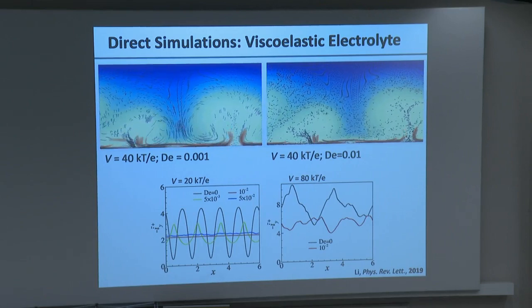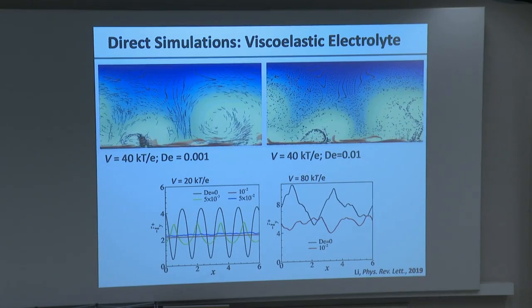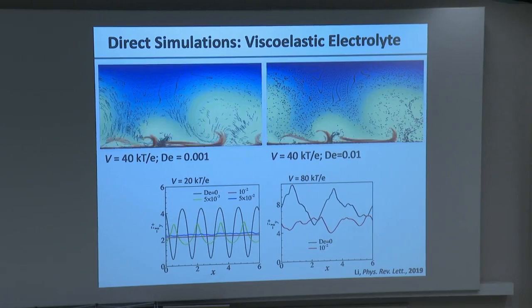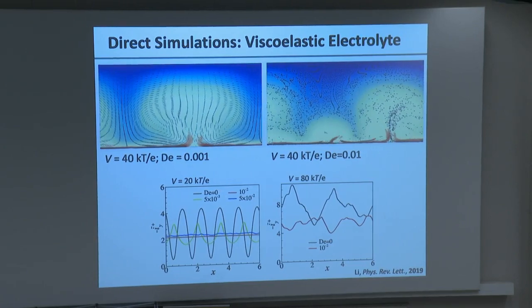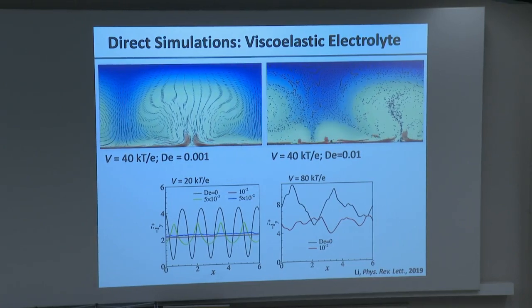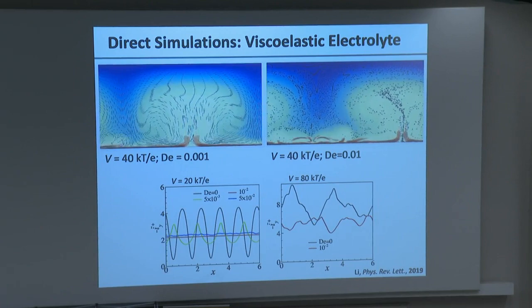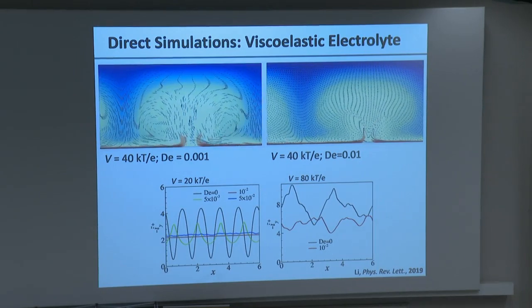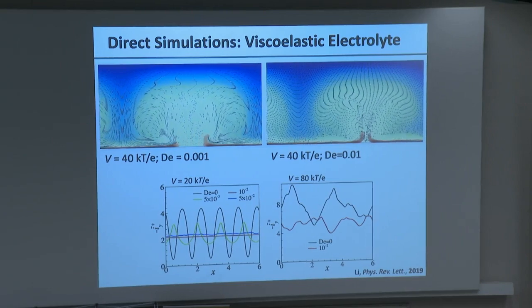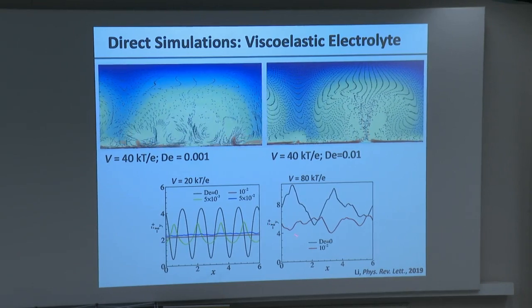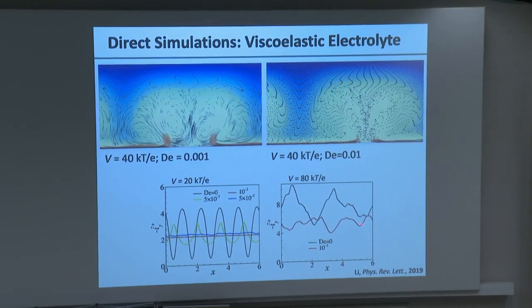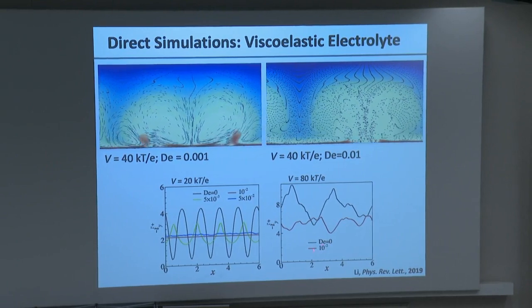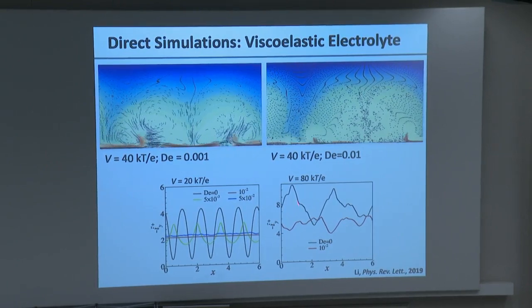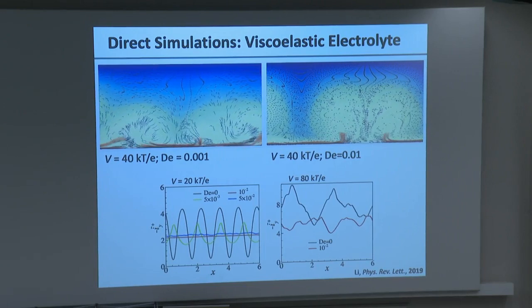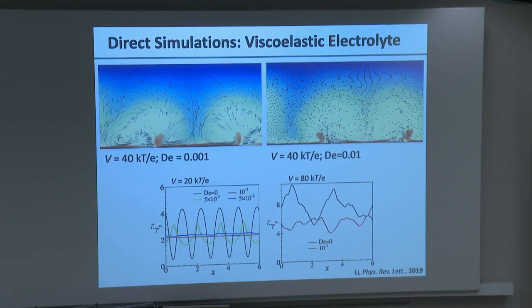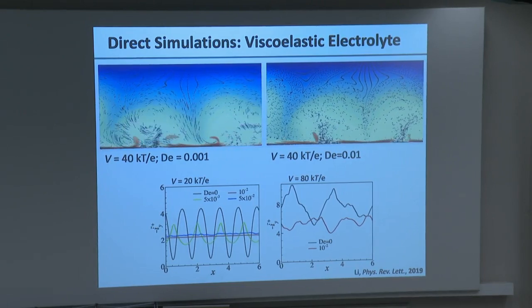So it's not that the polymer is stopping anything. The polymer is actually making it more chaotic by providing elastic stresses that are time-dependent and that are driving this sort of chaotic motion of the fluid in the vicinity of the surface, and that chaotic motion is causing the current, if we measure it as a function of position, to become generally flatter in the case of a polymer, where the Deborah number is non-zero, and more bumpy, with hot spots, in the case of no polymer, where the Deborah number is zero.